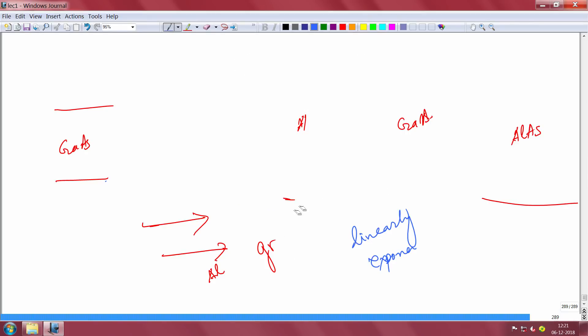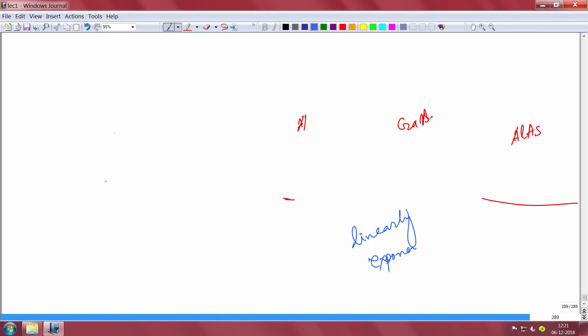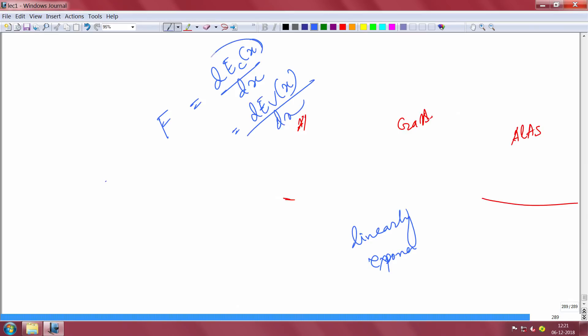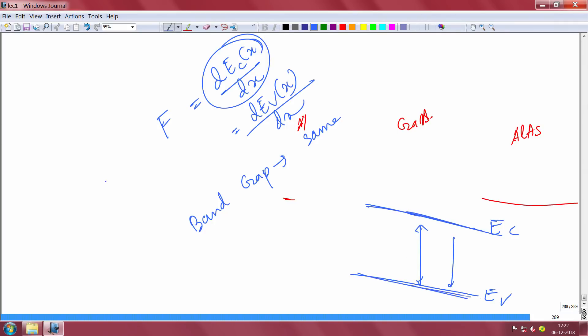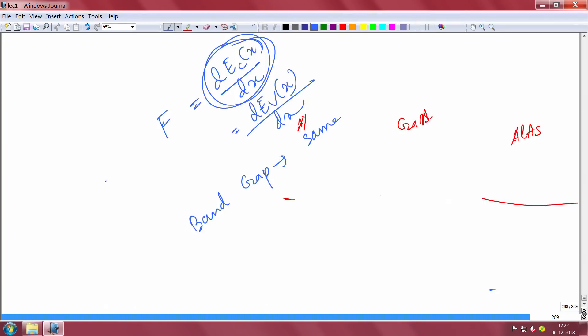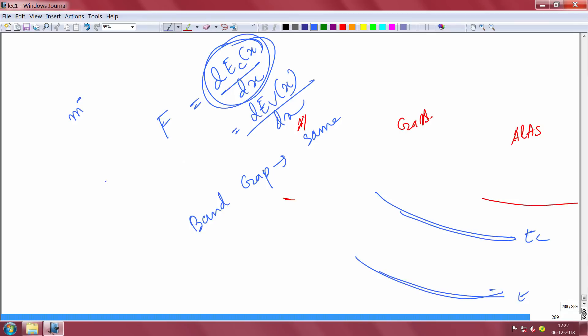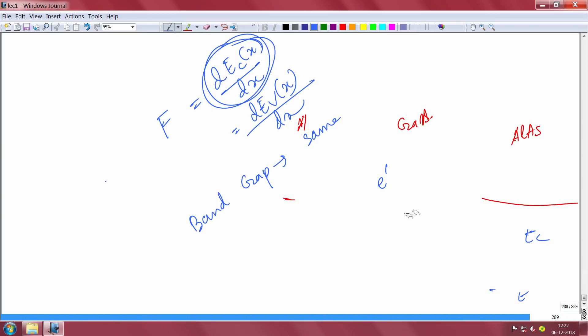The way you grade has a lot of implications. The electric field is defined as the slope of the conduction band. For electrons it is the slope of the conduction band; for holes it is the slope of the valence band. In a uniform band gap material, if the band gap is the same, the slope of the conduction band equals the slope of the valence band. With linear grading the field is constant; with exponential grading the field is also exponential. So the electron transit time from one point to another — and hence transistor speed — is affected by the grading scheme.